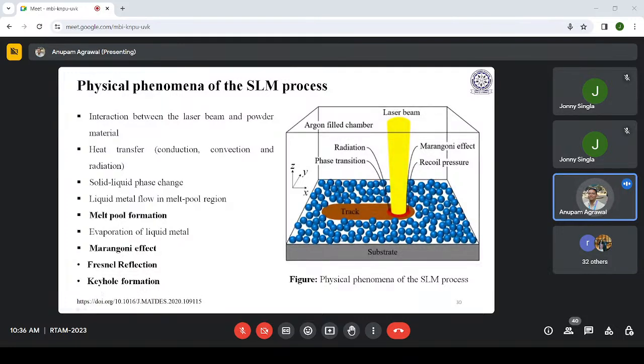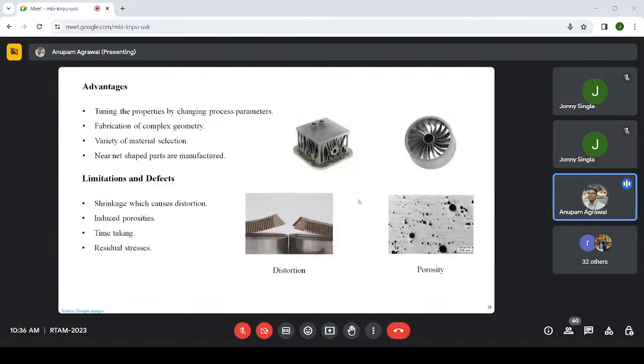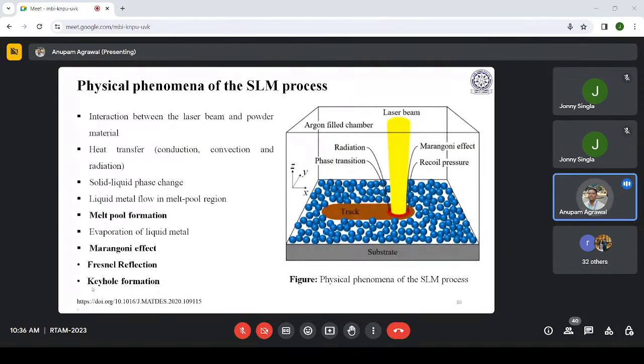And keyhole formation. I'm coming back to this slide. Many times in SLM based products, deep holes are created because of keyhole formation. Keyhole formation is the formation of long cavities because of the internal reflection of these laser beams inside the powder bed. As we keep building layer by layer, the laser beam can keep on getting internally reflected in very small keyhole-like places.